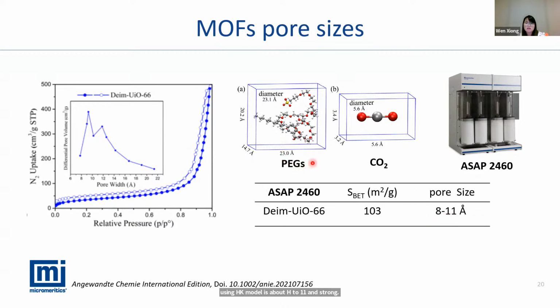So if we look at the diameters of different kinds of gas molecules, we are able to see the 8 to 11 angstrom pore size can be accessible to CO2 molecules, with 3.3 or 3.4 angstrom in diameter, but not able to let the larger molecules with a diameter of 20 or 21 go through. So those materials are able to separate CO2 from the larger molecules.